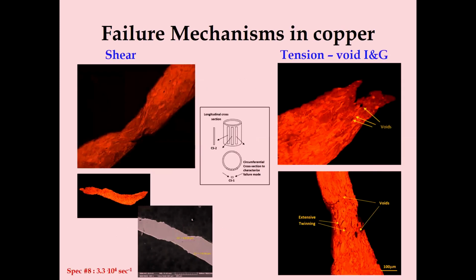So looking at the failure mechanism, if we look at copper, we look at the edges of these fragments. You could see here an example for the evolution of voids coming to a tension failure. We also have some arrested necks in these fragments, which become very interesting and nice to see. We could see the extensive plastic deformation here with a lot of twinning, evolution of voids. This is really just before the voids are breaking up the fragment. We could see also, on the other hand, some shear, a shear band evolved in some of these fragments. And again, we're going to do some extensive characterization, looking also at some statistics of these results.